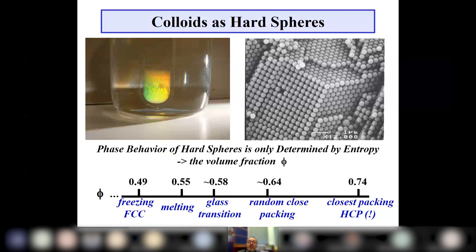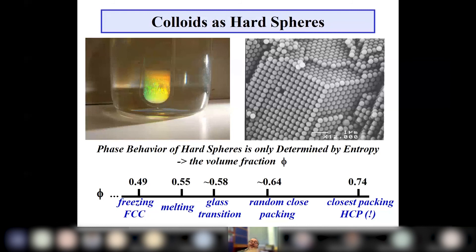The crystal that forms is a close-packed crystal. If you have a close-packed hexagonal plane and stack layers in crevices, calling that sequence A, B, C and repeating it gives a face-centered cubic crystal. Repeating as A, B, A, B gives hexagonally close-packed. The free energy difference between HCP and FCC is very small — on the order of 10^-3 kT per particle — with FCC being preferred, but often you find randomly stacked crystals.